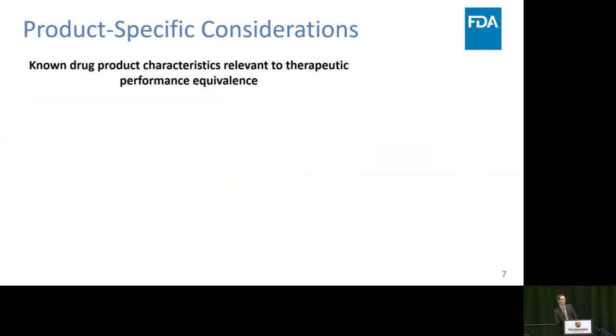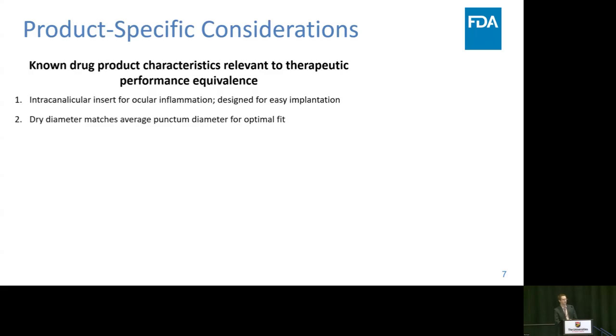So there's product-specific considerations for this particular product. The known drug product characteristics that are relevant to the performance here, among them, is that this is an intracanalicular insert for ocular inflammation, in the case of a dexamethasone insert, and it needs to be designed for easy implantation by a practitioner. The dry diameter of the insert matches the average punctum diameter for an optimal fit. This can introduce challenges in vivo studies again, because the real punctum diameters and canaliculus diameters have a pretty wide range in patients.